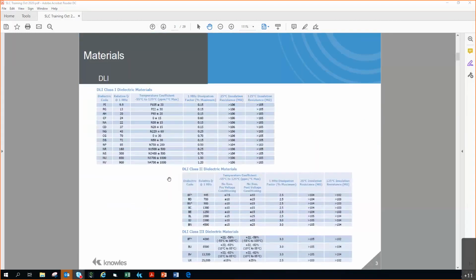So really, what everything starts with is the dielectric material. That's why we called ourselves DLI. We manufactured these class 2 and class 1 and class 3 materials over the years. All of these are in-house formulations. We have about 40 different dielectric formulations internally. We make it. We start from a raw powder form, and then we mill it, we tape it, we dice it, and we fire it. So it's all done here in the facility at Cazenovia.